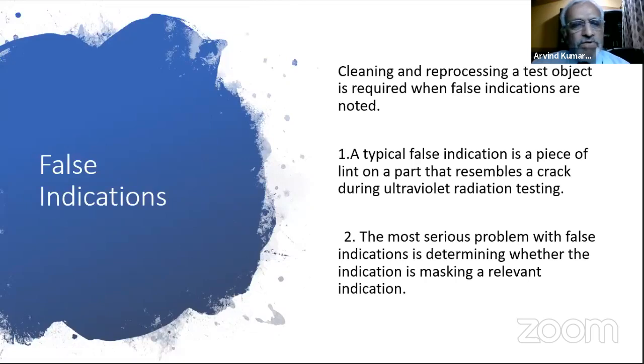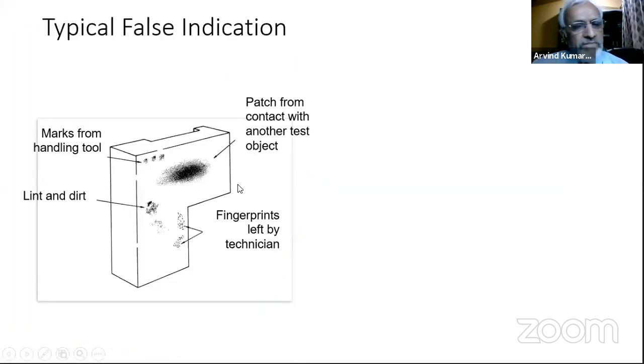Now, one thing we should see when it is a false indication is that it should not be masking the real relevant indication. If you have a false indication, fine, but it should not mask the relevant indication, otherwise you are going to miss it. Now, some indications which are false will appear like this: tool marks, thumb impressions, patchwork like this, finger impressions like this, or the impression can come from a dirty cloth, something like that.